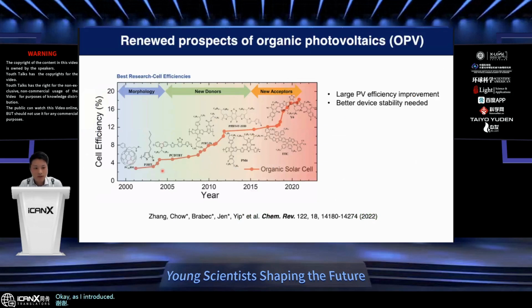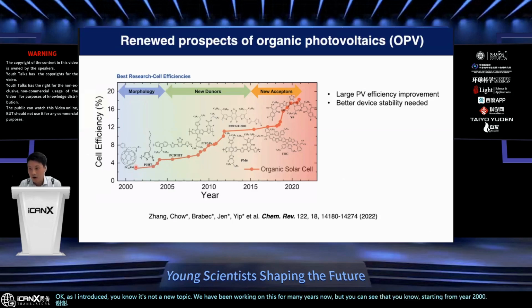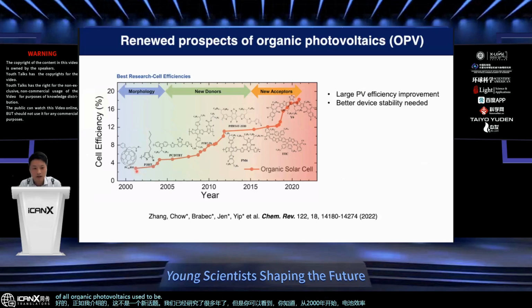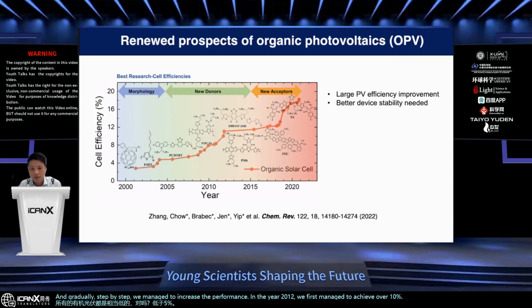Okay, as I introduced, it's not a new topic. We have been working on this for many years now. But you can see that, starting from year 2000, the cell efficiency of all organic photovoltaics used to be pretty low, right? Way below 5%. And gradually, step by step, we managed to increase the performance. In the year 2012, we first managed to achieve over 10%. And then, more or less, there was a plateau for maybe 5 to 6 years where there wasn't really that much improvement. But clearly, you can see that, starting from 2018, suddenly we managed to find the magic ingredients, right, which enabled this really rapid improvement in efficiencies.